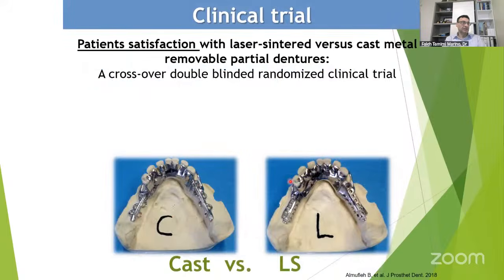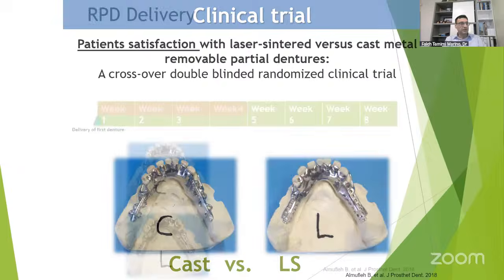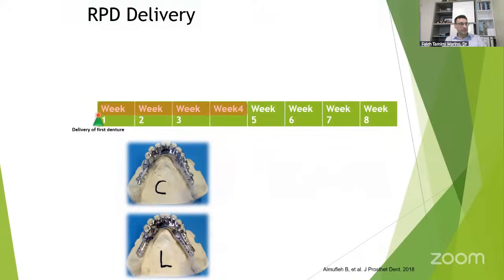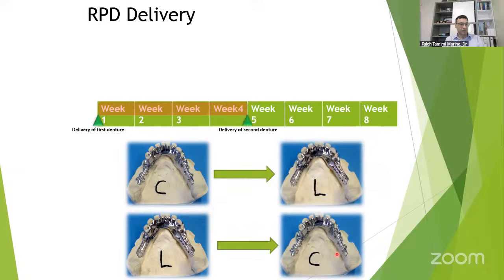We get a model from the patient, and that model we scan it, and we fabricate a laser sintered partial denture framework, and from the model itself we can fabricate a cast partial denture. So for each patient we fabricate two dentures, one that is fabricated by laser sintering and the other one by cast. Then we give one of the dentures, randomly, to the patient for 4 weeks, and then after 4 weeks we switch and give them the other denture.